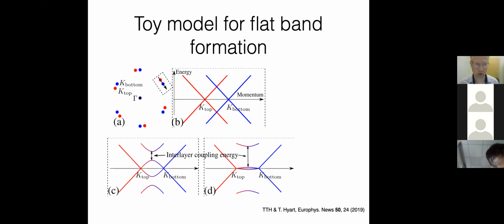Now if you put in a coupling, then all crossings try to become avoided crossings, like what happens in the C here. The size of this avoided crossing is fixed by the interlayer coupling, but the distance between these K points is fixed by the twisting angle. So you can find a certain magic angle where this avoided crossing size is exactly the size of the distance to the next level. And this is basically the magic angle.